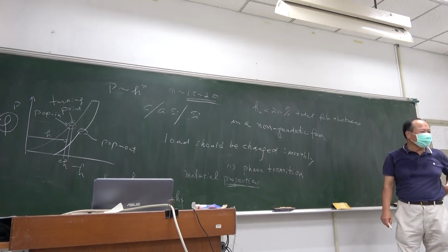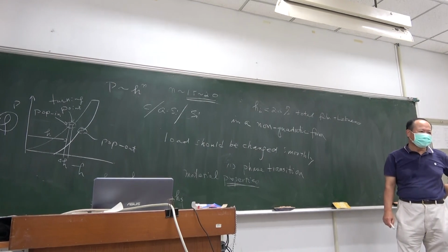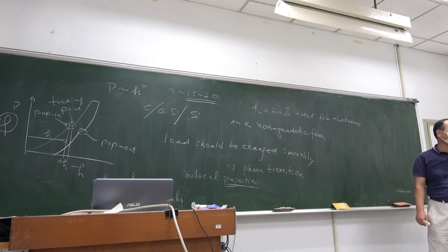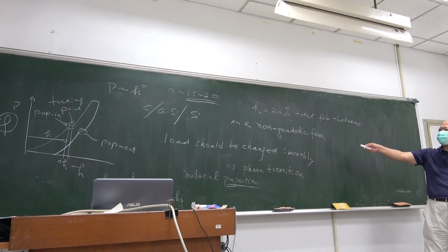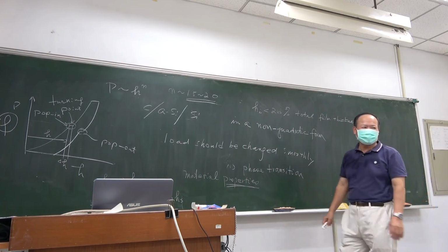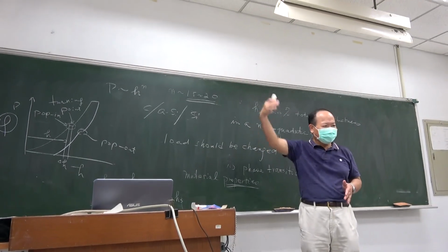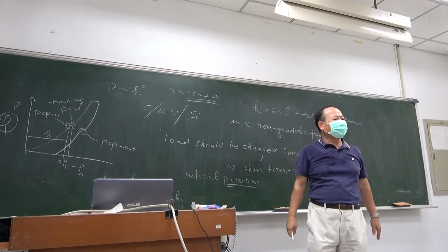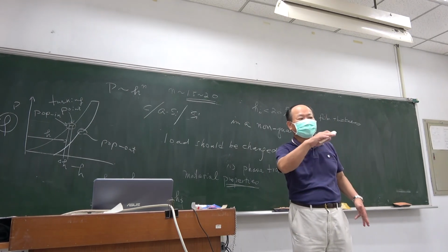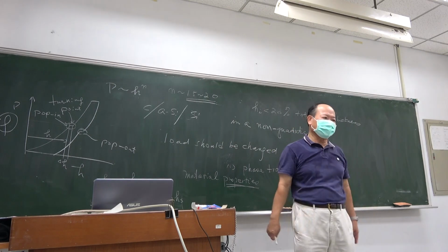So in modern times, the films become thinner and thinner. In this case, you'll find it is very hard for you, because 20% of your total film thickness becomes very small. If it is very small, there is the size effect. Last class we showed the size effect, which includes your residual stress and your surface roughness, which will influence your indentation.